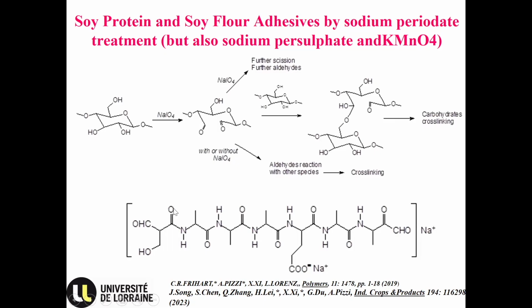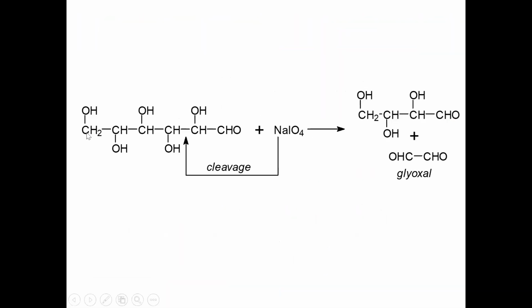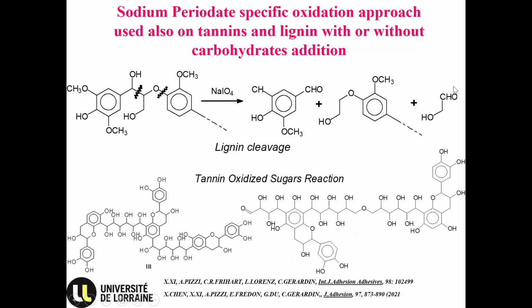So if you've got soy flour, you can actually obtain a very good adhesive in this way. This work was initially initiated by the Forest Product Laboratories in Madison, Wisconsin, but we actually clarified between ourselves the chemical reason why it worked. For instance, you produce aldehydes that are then cleaved and rearranged into glyoxal or other things. But you also get much bigger non-volatile aldehydes that are actually quite more convenient.